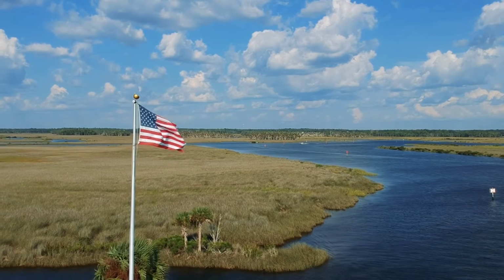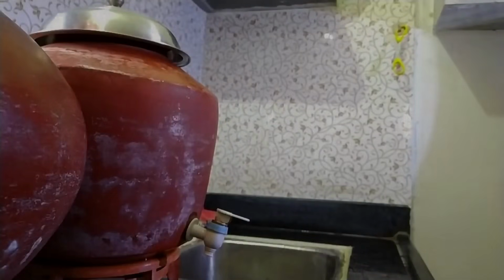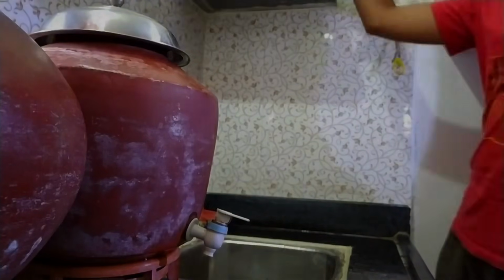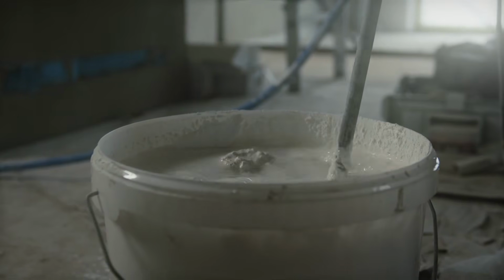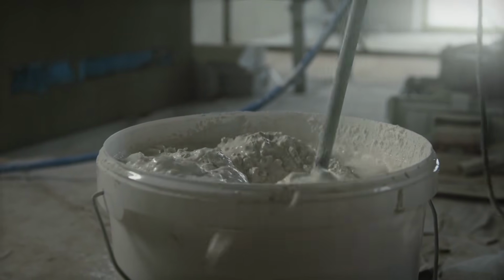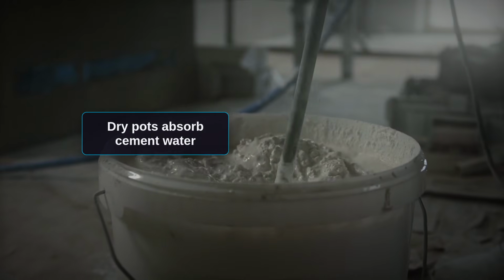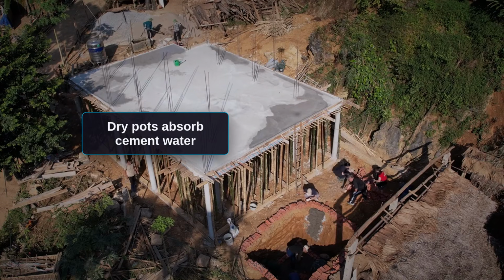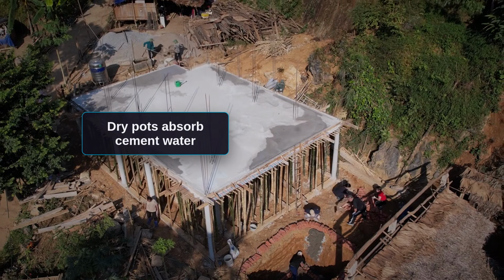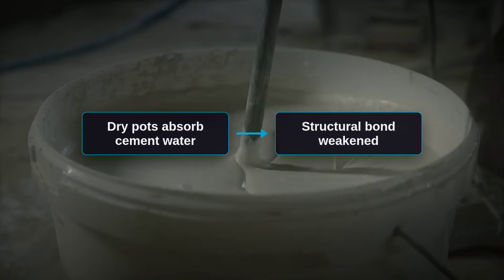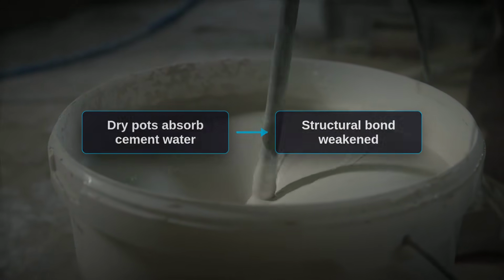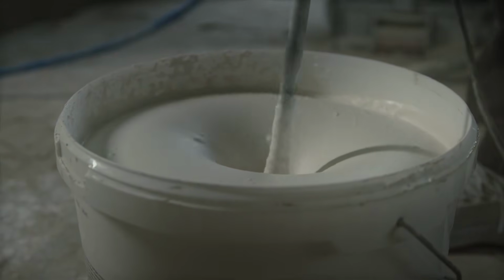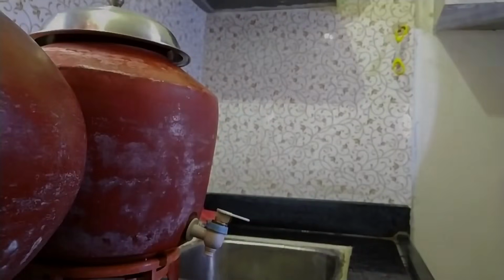So now let's talk about how you actually do this correctly, because knowing the physics isn't enough. There are specific failure modes that show up even in favorable climates, and most of them are avoidable with simple procedural discipline. The first critical error is using dry, unsoaked pots. When you place a dry clay pot into a fresh concrete pour, the porous clay immediately begins wicking water from the cement slurry. This localized dehydration weakens the cement matrix immediately surrounding each pot. The bond between pot and concrete is compromised, and the structural assumptions of the slab are no longer valid.